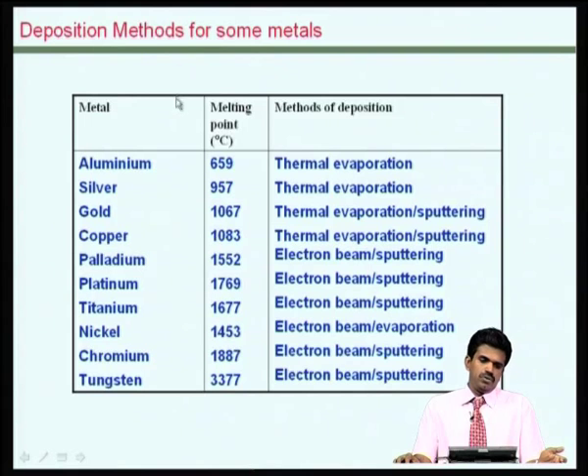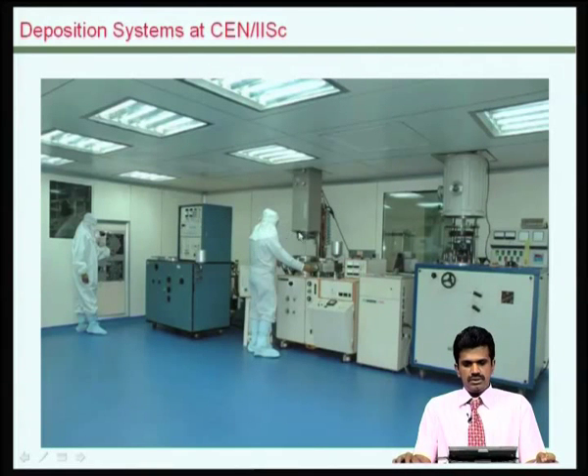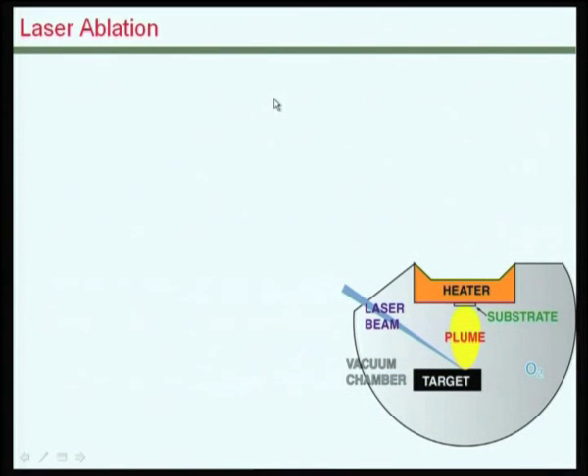And we look at how various materials, or in this case metals, could be deposited. We can look at them from the point of view of their melting points under standard conditions, and as you could see, aluminum having a relatively lower melting point can be deposited using thermal evaporation techniques, and materials having higher melting points would require other ways of melting or sputtering kind of approaches for their deposition. What you see here is a set of deposition equipment that are available at IISc, where you can use sputtering or evaporation kind of techniques for depositing various films.